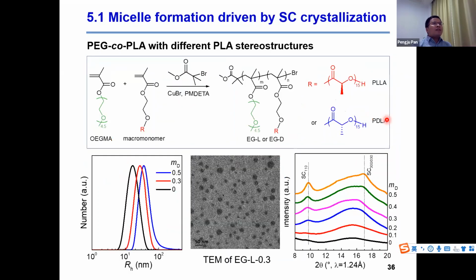And in this part, we first study the micelle formation and stability controlled by stereocomplex crystallization. We use a random graft copolymer of OEGMA and PLA or PDLA. This amphiphilic copolymer was prepared by ATRP from OEGMA and PLA or PDLA macromonomers. We then prepare the micelle solution from the homocrystalline copolymer or the mixed copolymer containing PLA and PDLA. The copolymer can form micelles in dilute solution.